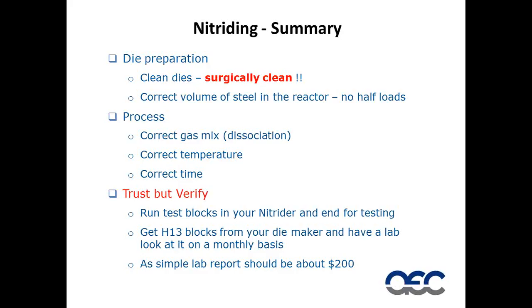You should be able to get a simple lab report with a picture of the nitrided layer telling you if there is a white layer formed, how thick the case depth is, and a few provisional hardness levels, just to tell you everything's right. Should cost about $200. If you don't have a local lab that can help you out, I'm sure that the Hydrotechnology Center would be happy to assist by doing these tests in exchange for some money. This is a service that Hydro is happy to offer to the industry if you need it. And if you do, contact me after this webinar and I'll put you in touch with the guy that runs the lab and you can talk to him about your needs.